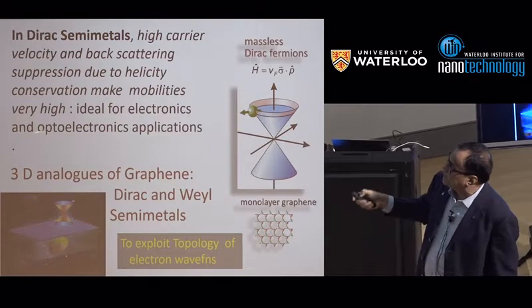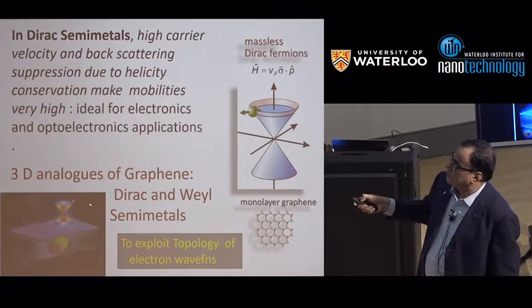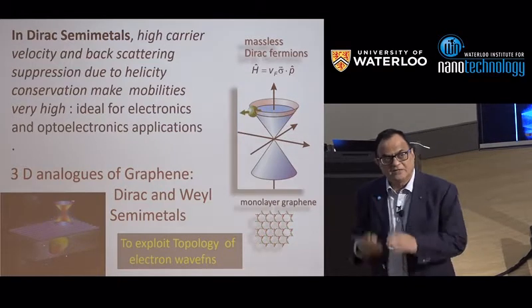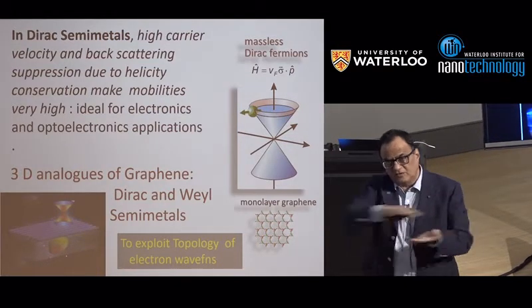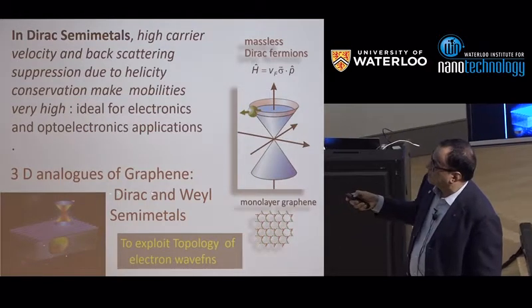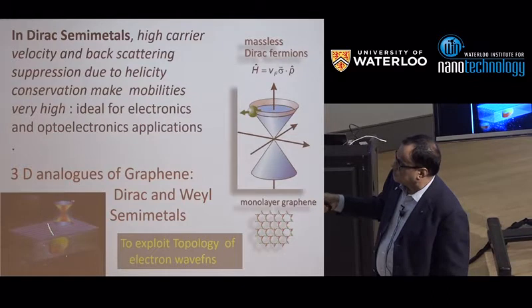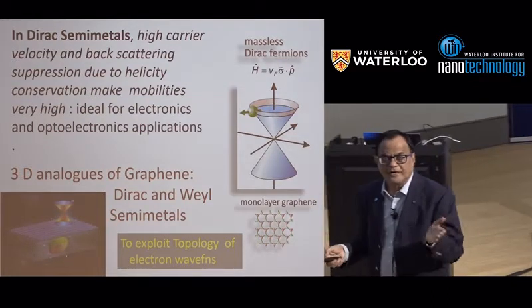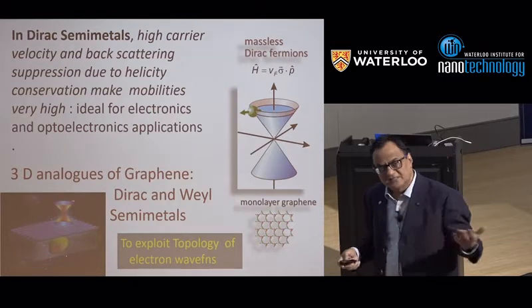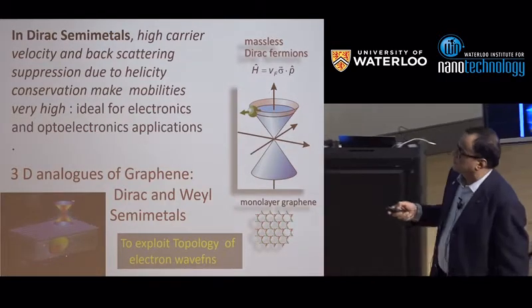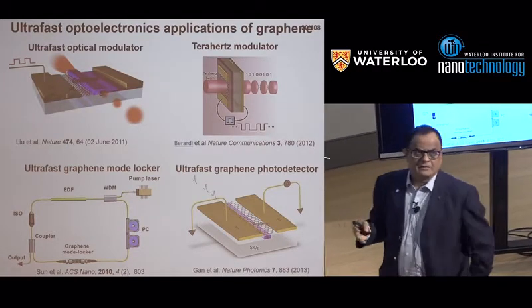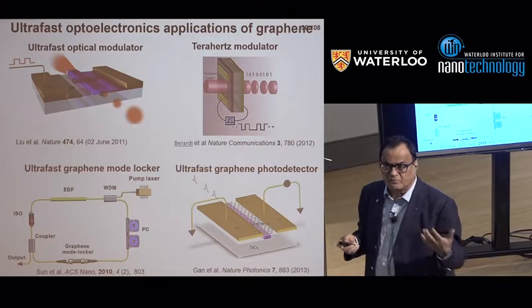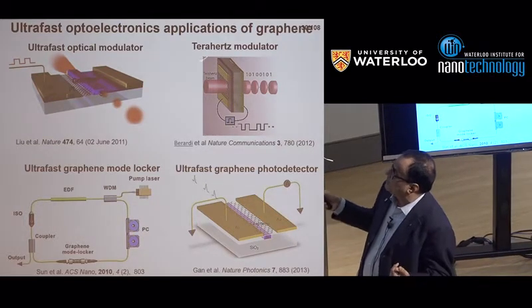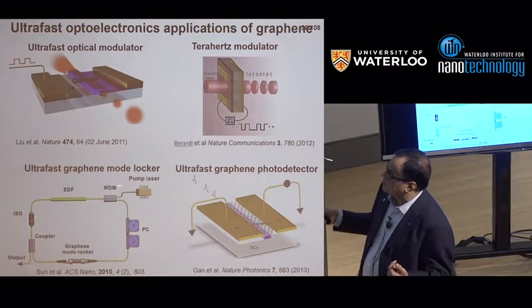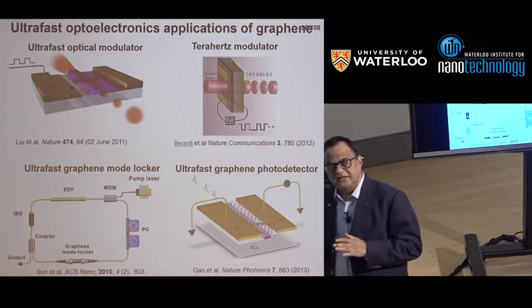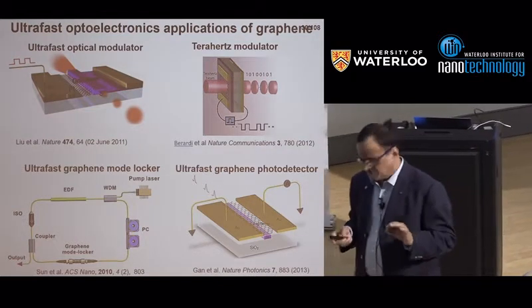And more importantly, it has now opened up a whole avenue for the 3-dimensional analog of graphene, where the Dirac cone is in the bulk, not on the layer alone. And we have been looking at what they call Dirac and Weyl semimetals, which is a topological feature. So this is the idea now, to combine topology of the electronic wave function and see whether we can add some interesting properties. So already there are applications promised and demonstrated, some of them, for example as an ultrafast optical modulator, terahertz modulator, photodetector, and so on. So all these applications need quantitative information on carrier relaxation pathways.